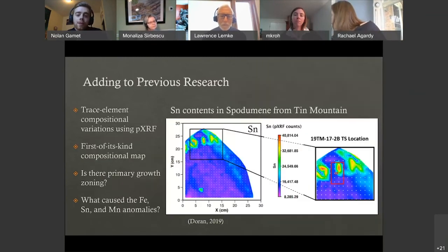So adding to previous research, Christina Doran and Dr. Monaliza Sirbescu used trace element compositional variations with the portable X-ray fluorescence to try optimizing and calibrating this method. With this data, they were able to recreate first-of-its-kind maps with samples of this size, roughly 30 centimeters by 30 centimeters. To make these maps, they used the PXRF counts, as seen here.